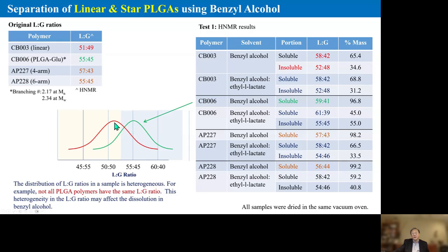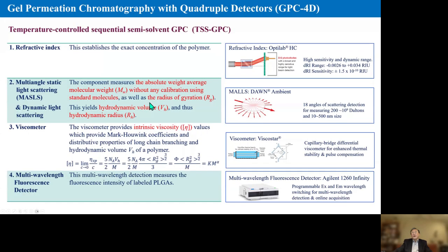So if we mix the two and separate, for example, using a certain semi-solvent, in this case the light gray area, then basically what we are separating is based on LG ratios. Of course, the molecular weight also affects the result here, but the semi-solvent is mainly for LG ratios. So we can separate the two different samples based on LG ratios. Now, once we separate them, we can further characterize using GPC4D.